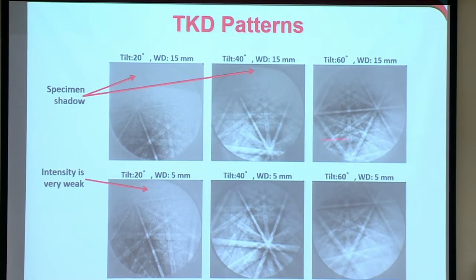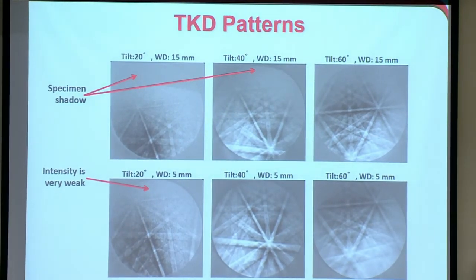So here's the kind of patterns we get. They look a lot like EBSD patterns, although they do tend to show a little more distortion in them. If you look very carefully, that's very thin at the top and a little thicker at the bottom. That's actually more obvious on this one here.